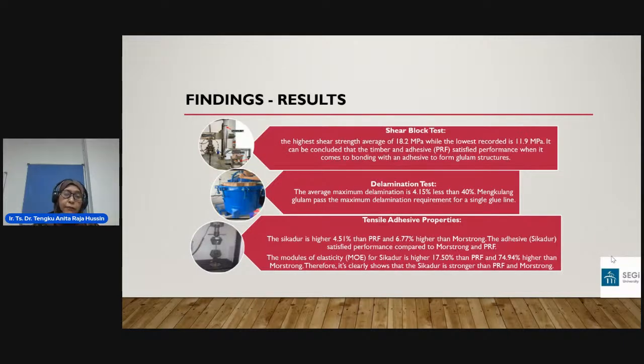All right, the findings of the results: we have the shear block test. The highest shear strength average is 18.2 megapascal, while the lowest recorded is 11.9 megapascal. It can be concluded that the timber and adhesive PRF satisfied performance when it comes to bonding with an adhesive to form glulam structure. The second one is delamination test. The average maximum delamination is 4.15%, less than 40%. Mengkulang Glulam passed the maximum delamination requirement for a single glue line.